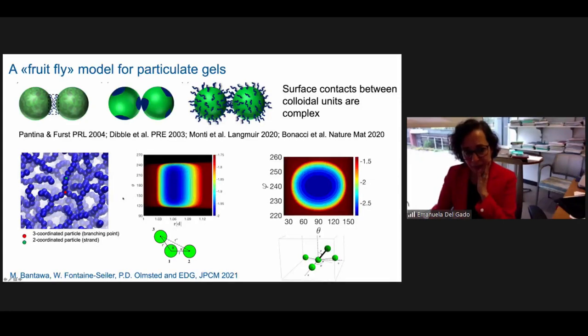And so now it's interesting. So changing the gelation protocol, changing the volume fraction of the particles that we have, we will have different degrees of frustration that emerge in our system and in the growth of this different type of structural element in different parts of our simulation box. What we can do is that from the analytical form of our interaction, now we can compute the elastic energy cost in deforming these structural elements alone. So if we take a chain made of 3 particles, how much energy it costs to bend it or to stretch it, and this is this contour plot that you see here. Or if you take a branching point, how much it costs to deform it by changing the angles.